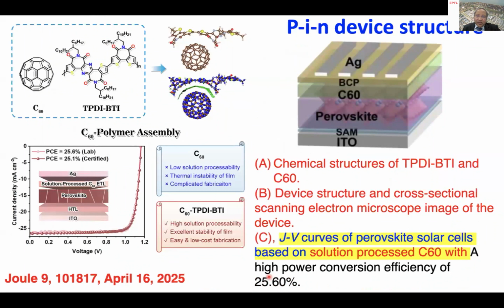PIN configuration, where I mentioned the PIN is a hole transporting material we have to deposit, followed by the perovskite, followed by the ETL layer as shown here. And we have a BCP, this is a buffer layer, and we have a silver. This is a PIN configuration. So to deposit the C60, usually people use the sublimation technique, followed by the BCP.